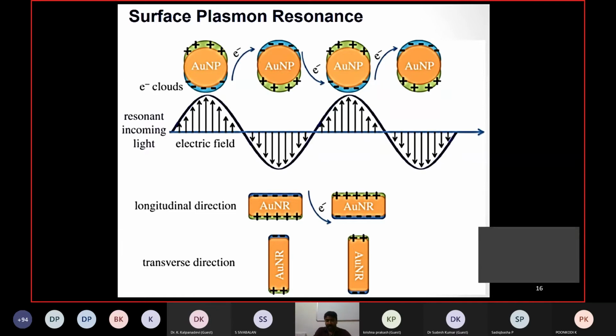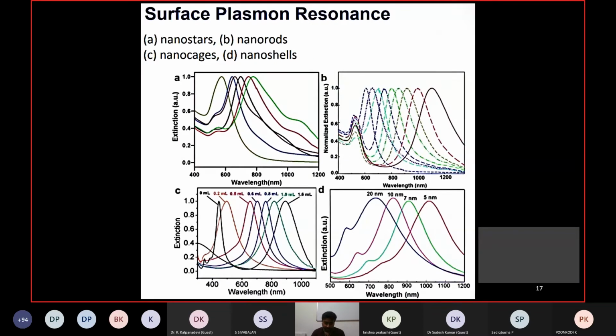The surface plasmon band is common for gold and silver nanoparticles. These metallic nanoparticles have surface plasmons, and they can be excited using NIR radiation. For instance, the near infrared radiation allows the heating of the structure. That radiation is absorbed and the relaxation allows the heating of the particle. The absorption of the NIR radiation is measured in terms of the absorption, and the heating of the nanoparticle is measured in terms of the photothermal conversion efficiency.